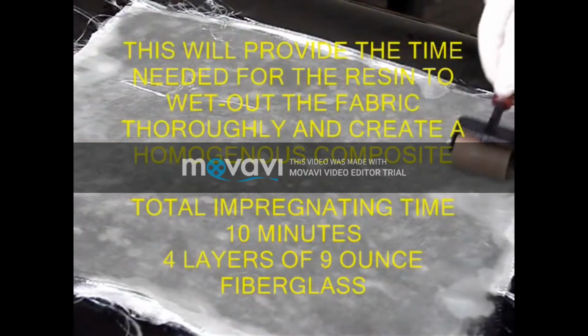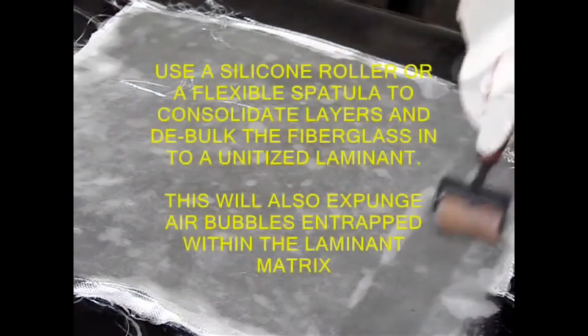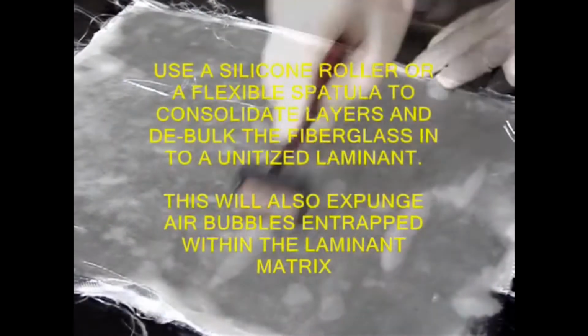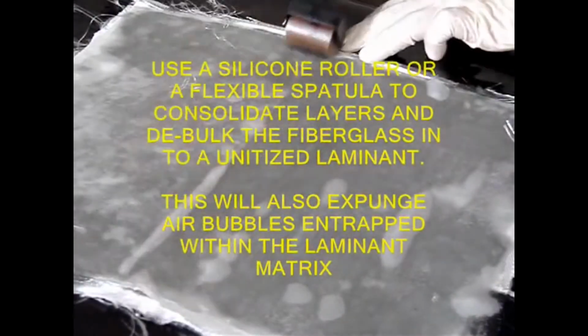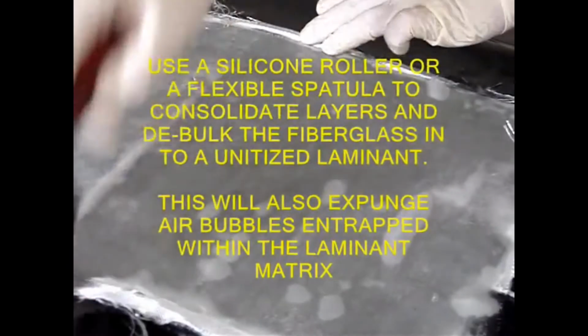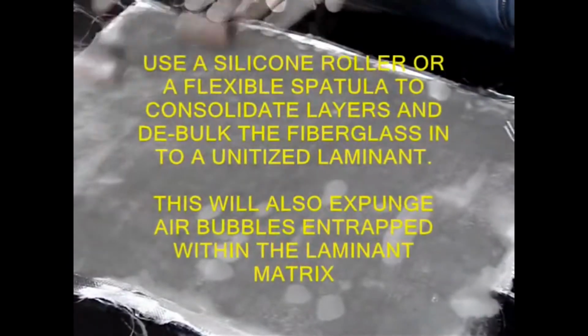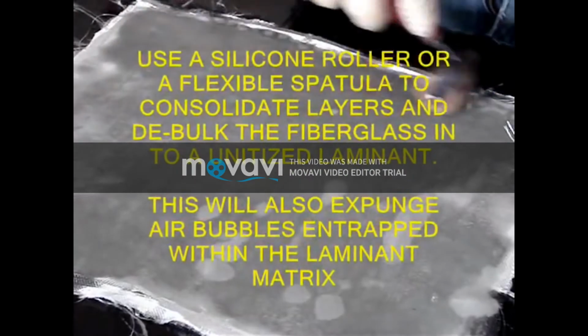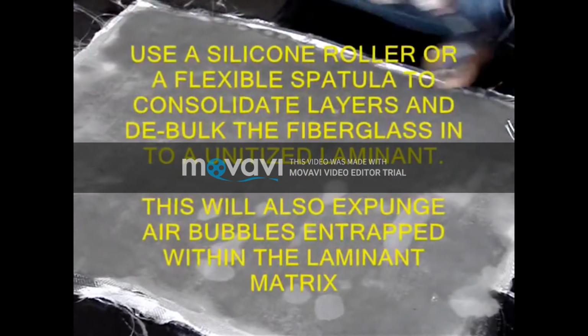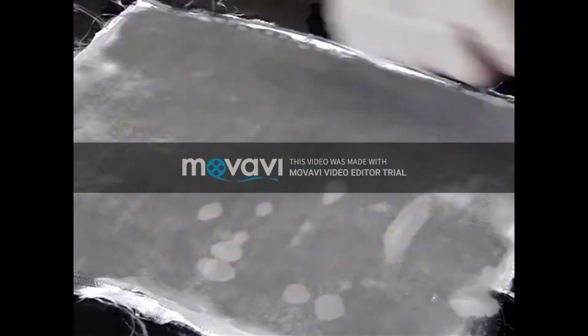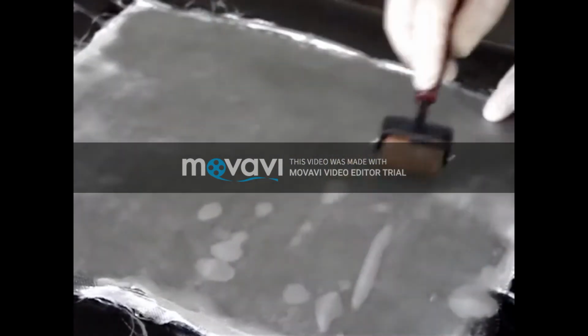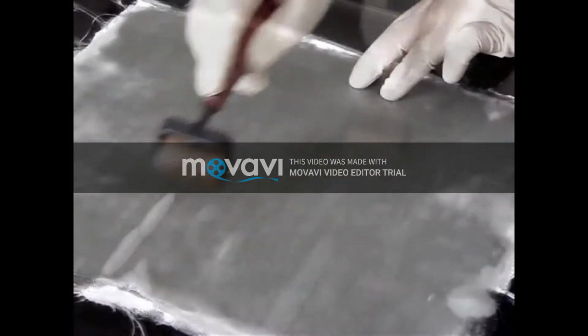The total impregnation time is 10 minutes. We have to use a silicone roller or a flexible spatula to consolidate layers and debulk the fiberglass in a unitized laminate. This will also remove the air bubbles trapped within the laminate matrix.